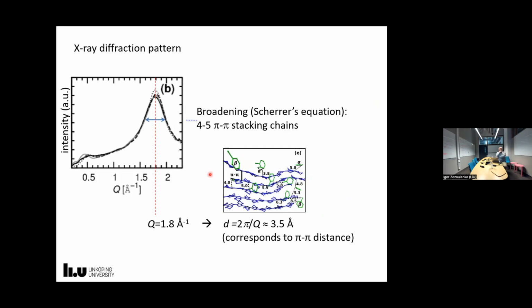And then what you can do, you can calculate the X-ray diffraction pattern. You see this X-ray diffraction peak, and by the position of these peaks, you can recalculate according to the Bragg formula into the spacing. Basically, the spacing is the pi stacking. So, as I said, chains are formed in crystallites due to the pi stacking between the chains. And again, the broadening of the peaks, the so-called Scherrer equation, tells you how many chains you have in a crystallite.